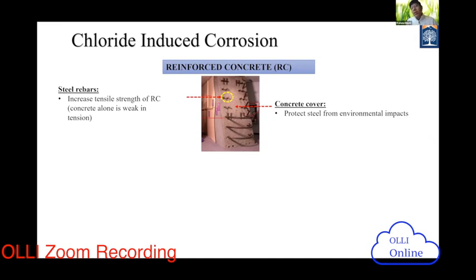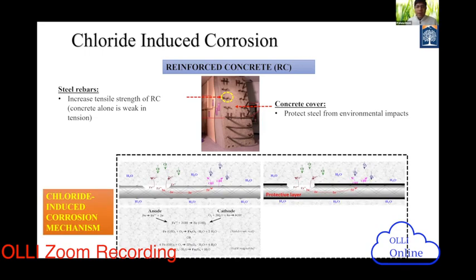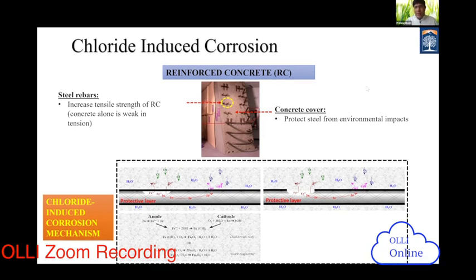So due to corrosion, concrete's tensile capacity starts to weaken. That is one of the major challenges. And we always see that some concrete covers are there. Cover means some amount of cushion before the reinforcement is placed. So if you have very little cover, then that is also a challenge, because if corrosion happens easily, then the rebar gets exposed, and then obviously the corrosion starts to propagate heavily, and the functional part will be gone. So this is the chloride induced corrosion mechanism. Again, I'll start to tell how the corrosion happens in concrete. In general, the first thing that comes to mind is that corrosion means the rust product.